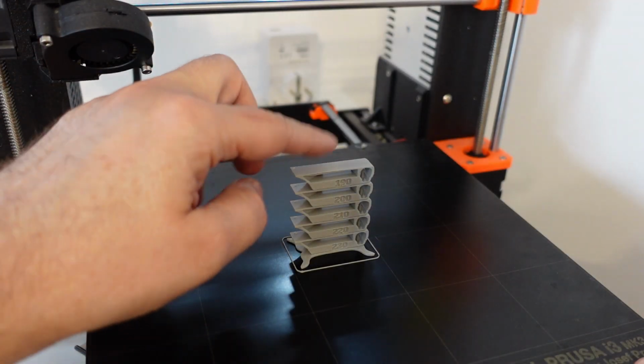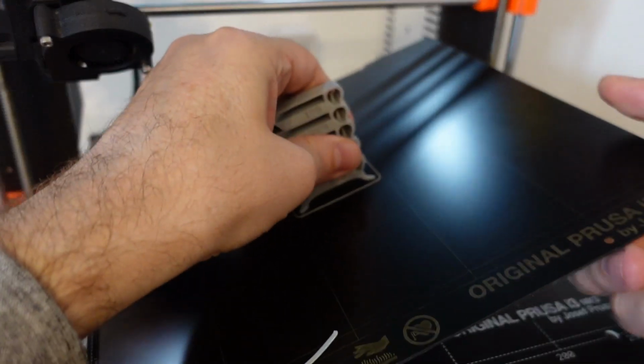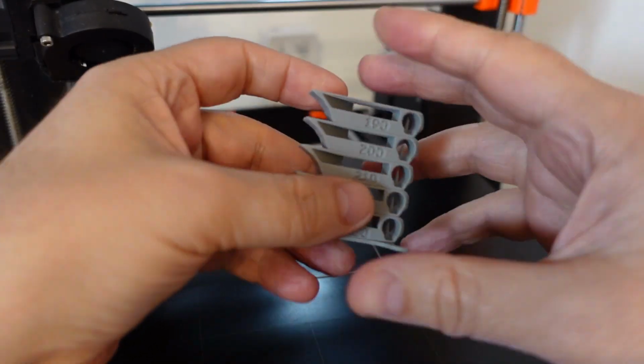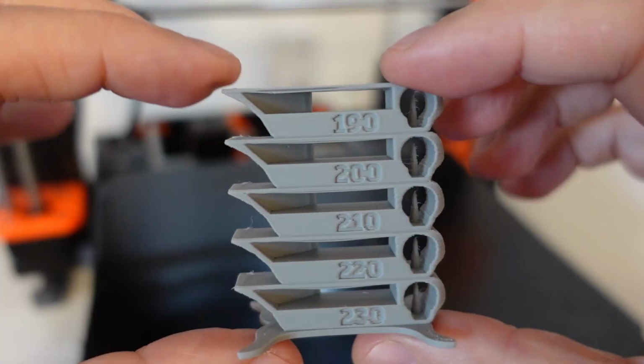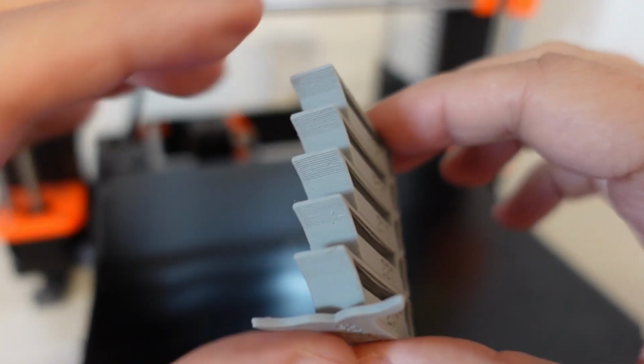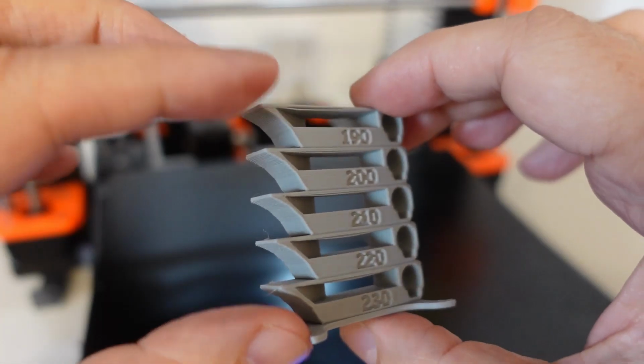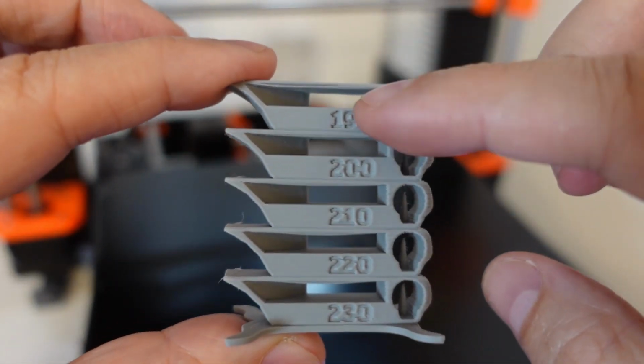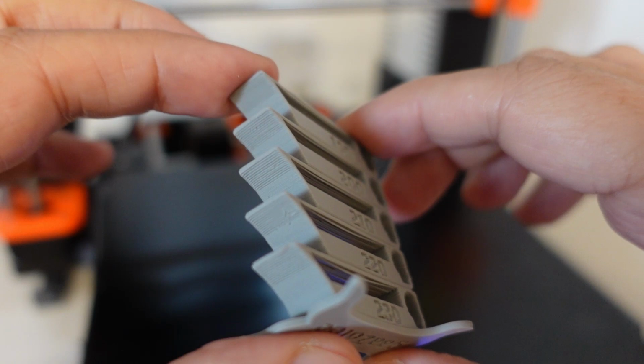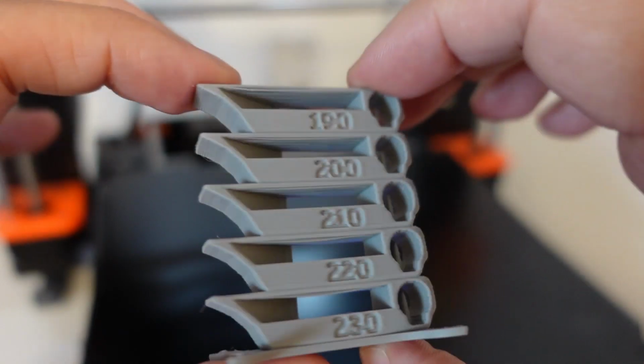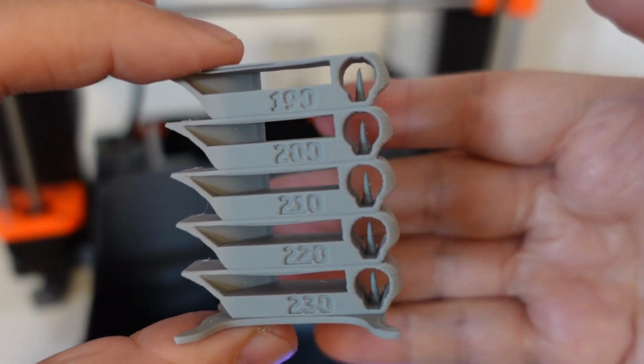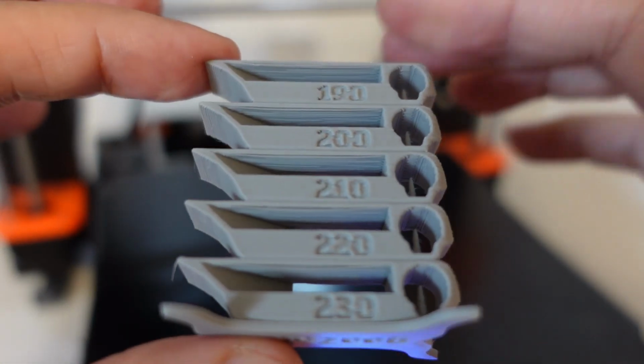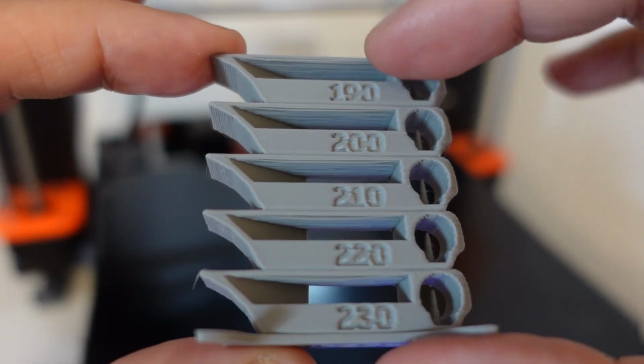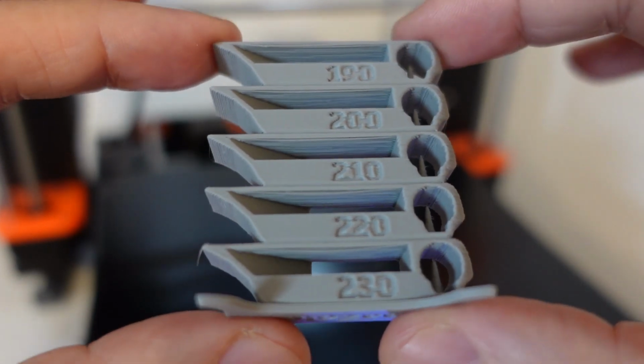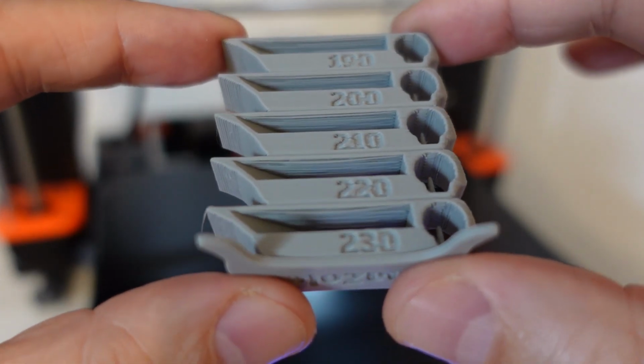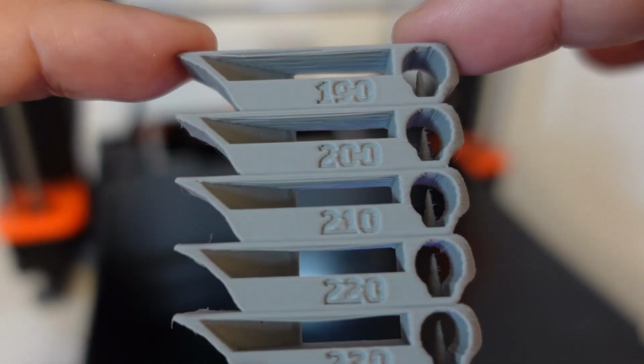Printing is finished. I was worrying a little bit about 190 degrees Celsius. And here it is, absolutely no problems with the printing from 230 down to 190. Perfect overhangs, absolutely no stringing at any temperature. Only I noticed that the bridging has a little bit bigger stomach than regular PLA. I'm not sure if it is visible on camera too.